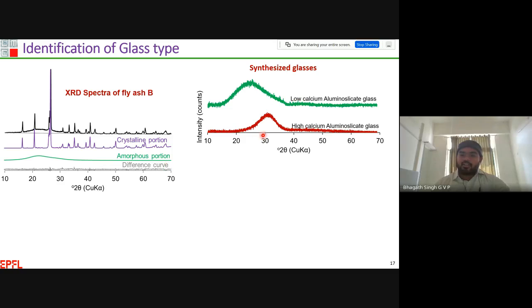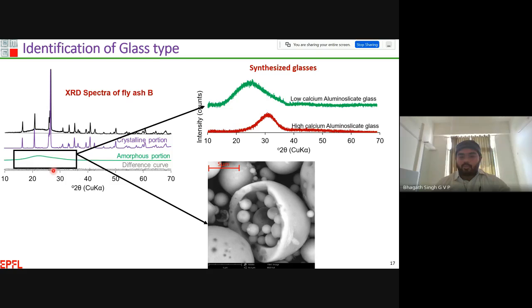Then I have synthesized some glasses, one a low calcium aluminum silicate glass and another a high calcium aluminum silicate glass. I measured the XRD signatures of these two glasses and compared them with our fly ash signature, the amorphous portion I have shown here. Our Indian fly ashes, especially the siliceous fly ash, contain the low calcium aluminum silicate glass, which has a well-defined center around the 2θ angle of about 22. And this amorphous hump is attributed to the plerospheres and cenospheres present in our fly ash.